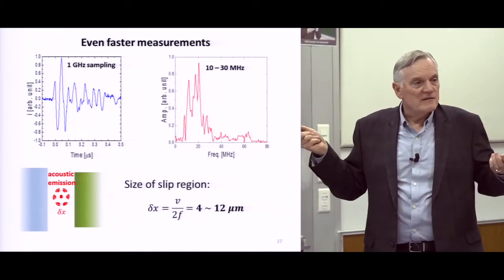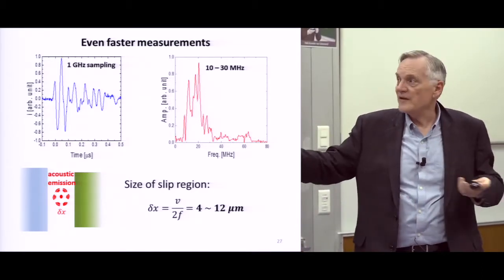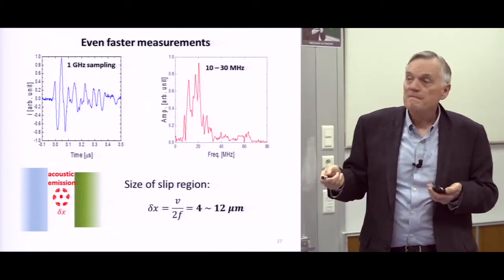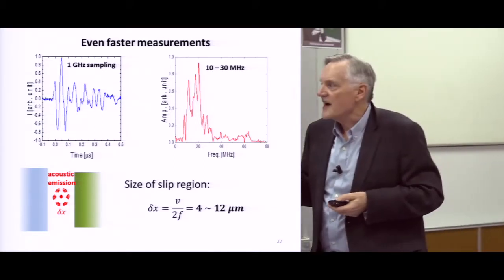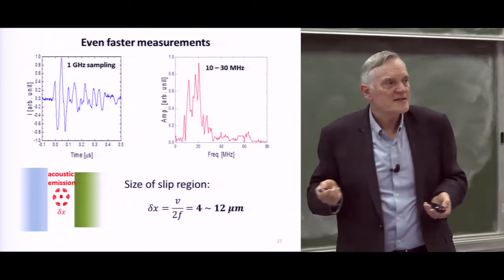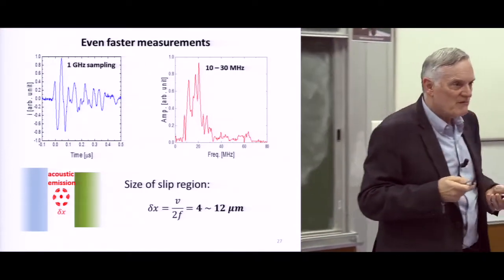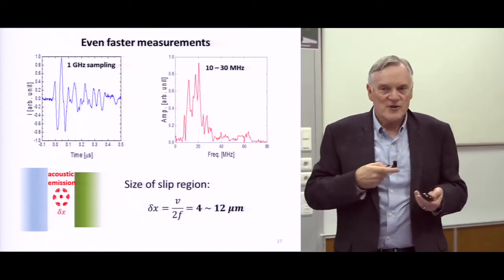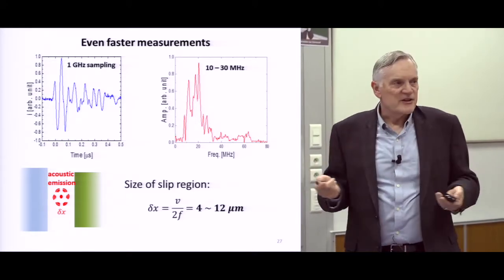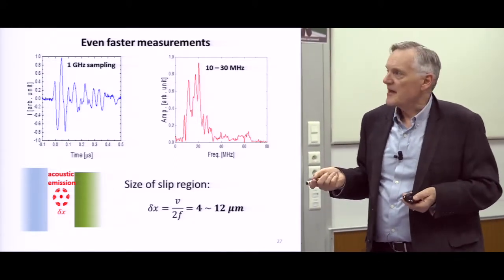And then it did it very fast and emitted sound waves, which is what you picked up, the acoustic emission. So that's the size of these very, very small, very, very fast slip events, which, as in almost everything, are due to dislocation avalanches. They avalanche and eventually they pile up and stop themselves. That's what we expect is happening.